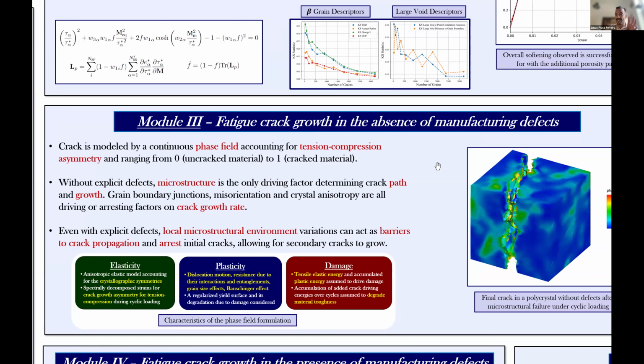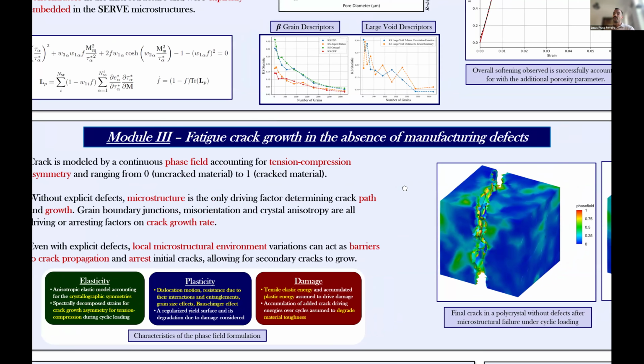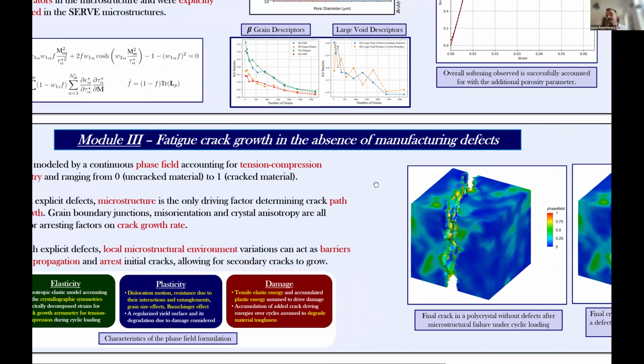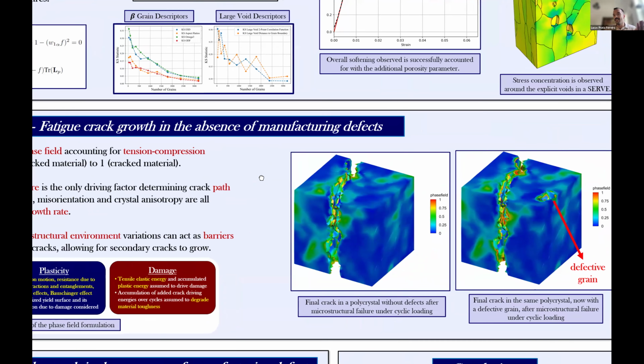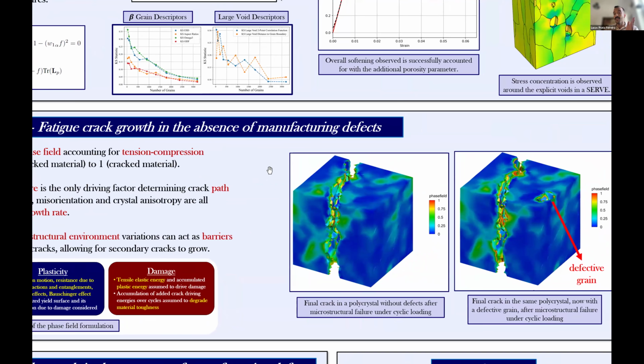And we wanted to assess if this phase field formulation would be enough to analyze the competition on driving cracks between the microstructural characteristics and the defects. Because what is normally stated is that, oh, if there's a defect, the crack is going to grow through there. But that doesn't necessarily happen because the microstructural environment of a defect can be arresting of the cracks.